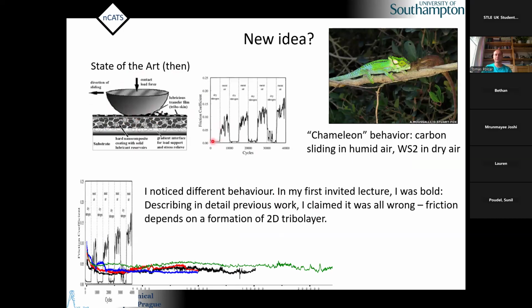And what they showed in an extremely well-cited paper was that in dry nitrogen, it was very, very low friction. Friction increases when you change atmosphere to humid air. But then if you go back to dry nitrogen, it will go down. So it can go up and down. They call it chameleon behavior. And then they said that this is sliding by tungsten disulfide, which is solid lubricant.